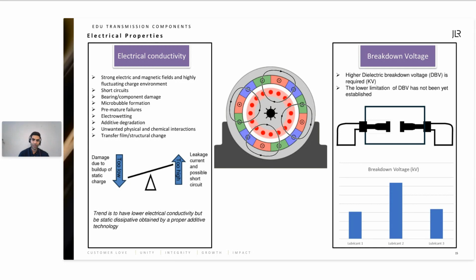And if the electrical conductivity of the lubricant and the dissipation factor are not working well, you would see all sorts of problems within the EDU, such as additive degradation, bearing and component damage, electric discharge, etc. And I have put an example of a test that we conduct to understand the behavior of these lubricants in high voltage scenarios known as breakdown voltage. It's an industry standard test where you put the lubricant and you apply high voltages around the lubricant to understand how the lubricant would break down or how it would degrade on the high voltages.